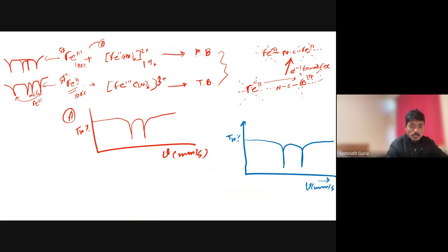Because of that, the external iron 2 added into the hexacyanoferrate system reduces the internal hexacyanoferrate, giving me iron 3 at the outer coordination site, and iron 2 at the inner coordination site, which is found in the Prussian blue.